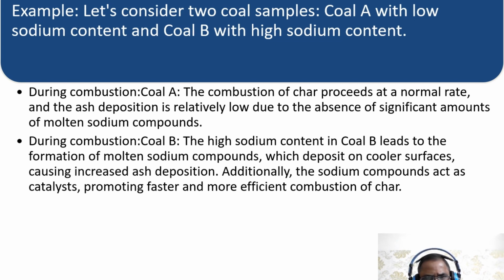Now let's shift our focus to coal B. Here the high sodium content leads to the formation of molten sodium compounds during combustion. These compounds deposit on cooler surfaces, causing a noticeable increase in ash deposition. But that's not all. These sodium compounds also act as a catalyst, promoting a faster and more efficient combustion of char.